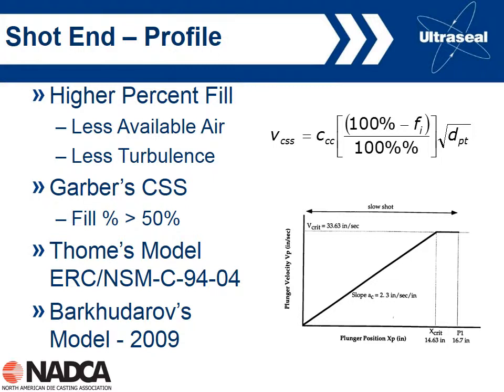This is where his equation shown here on the right-hand side comes from. And the idea was to basically calculate the maximum speed I can move the plunger at during the slow shot velocity. It's obviously based on the plunger diameter and the fill ratio. Bear in mind, as shown here in the middle of the slide, that Garber's calculation for the slow shot velocity basically only works for a fill ratio bigger than 50% or so.